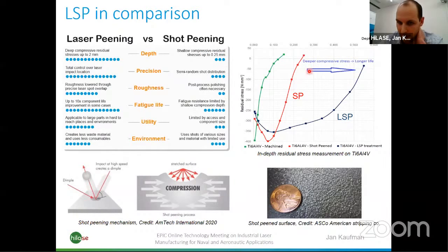You can also see it on the graph over here. This is the depth of the shot peened part. This is the depth of the LSP part, but this difference tends to be much greater. The next difference I'd like to talk about is the roughness you achieve after the process. So in the case of shot peening, the surface tends to be rather coarse, as you can, for example, see here, and some kind of post-processing is very often required, while in the case of laser shock peening, the roughness is not so bad, it's rather smooth, and you don't need any post-processing after that.